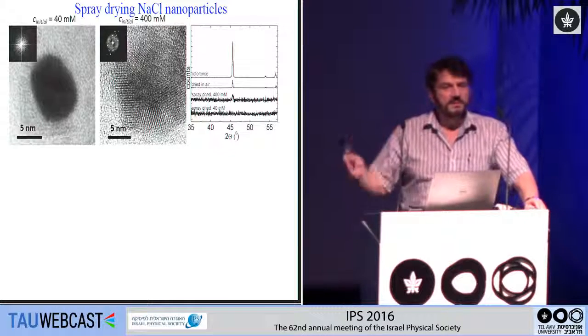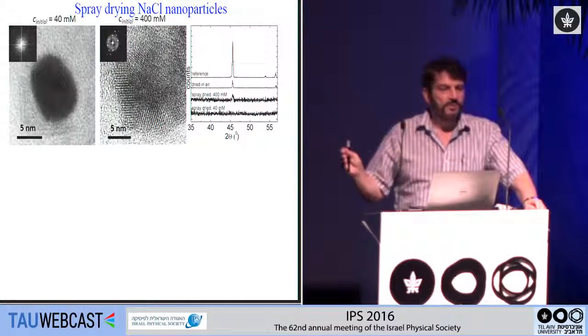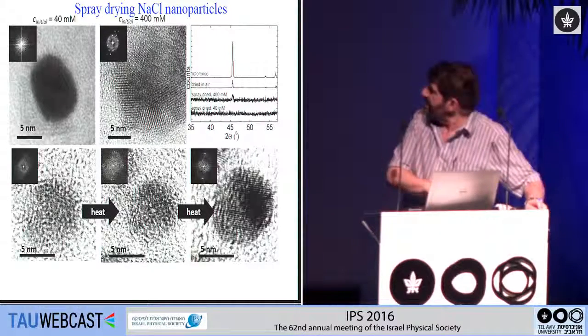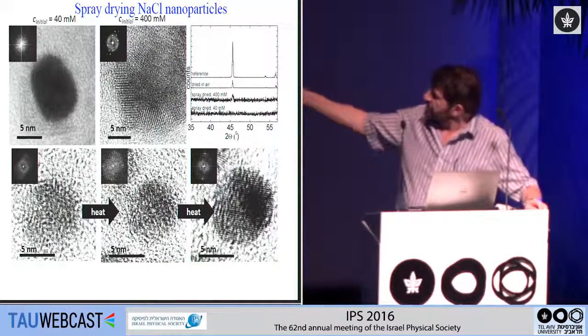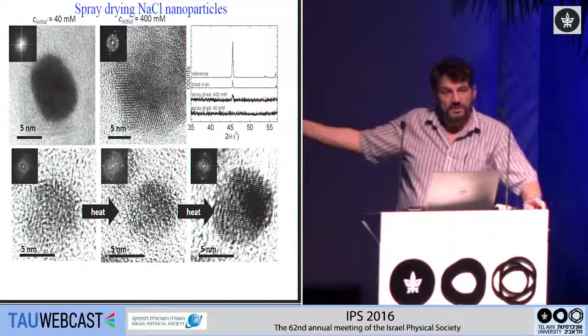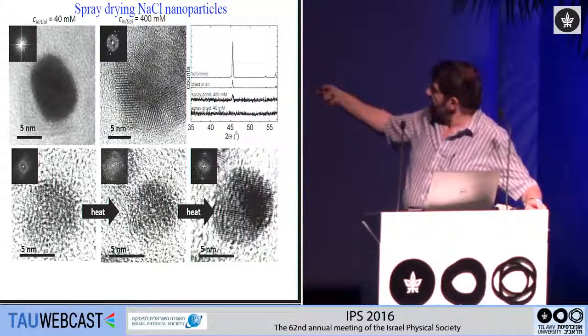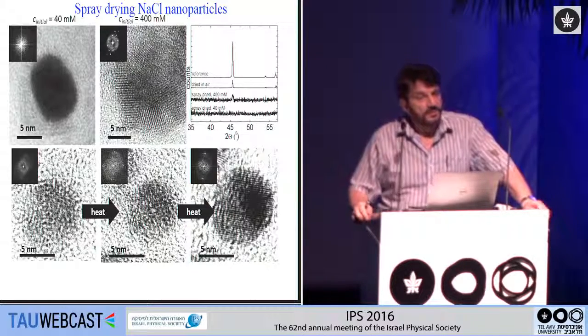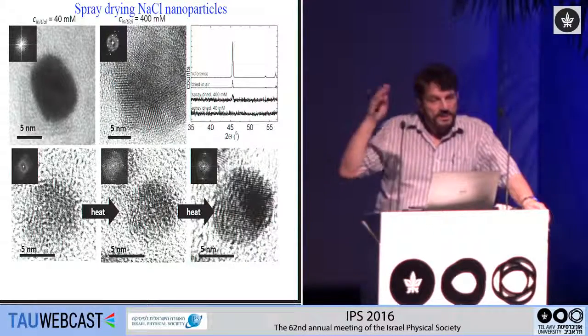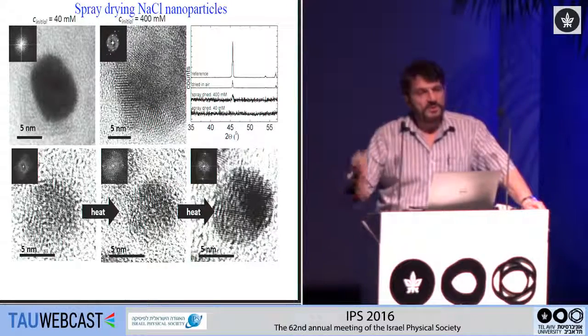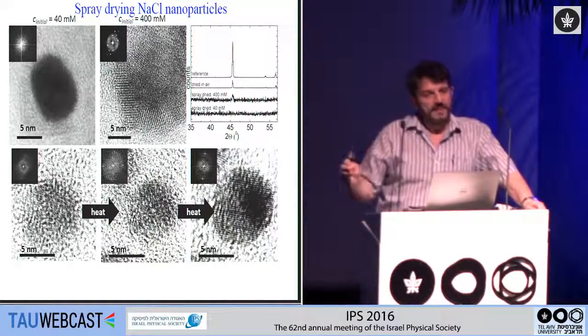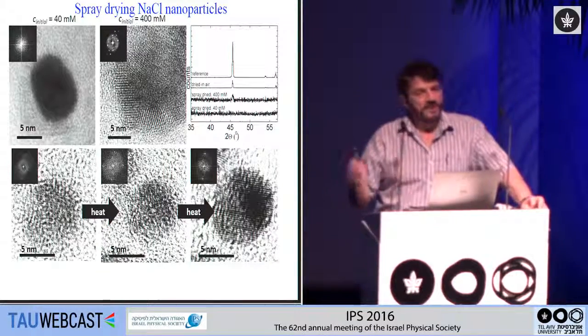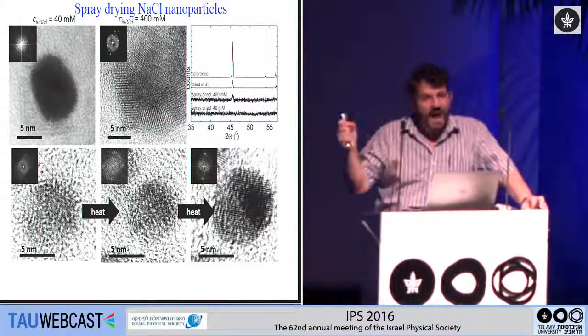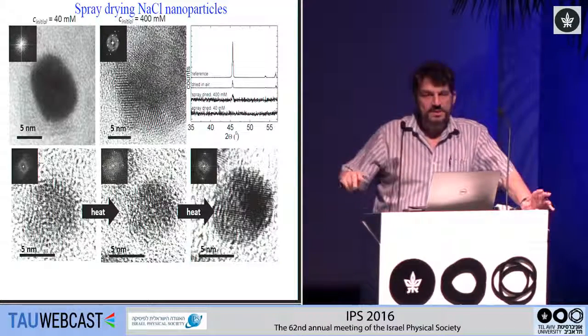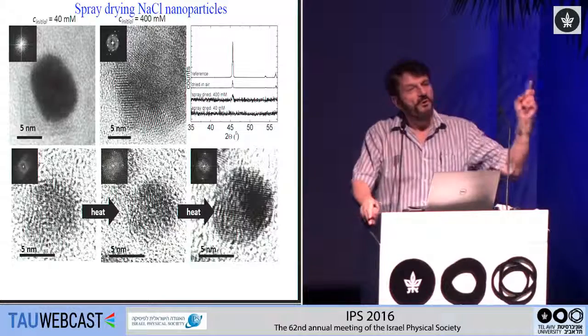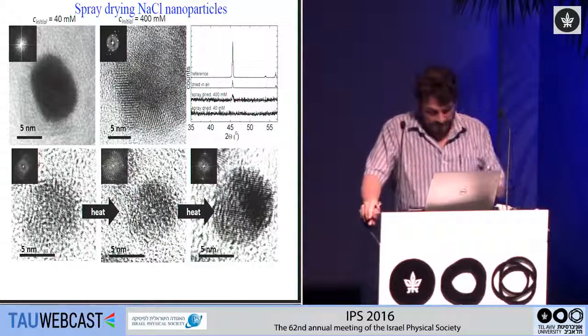If you make salt below 5 nanometers just by spray drying it, it's also amorphous. And here's some examples of the amorphous material. And just to prove that it's amorphous, we took an electron microscope and we heated it. And you can start to see that as you heat it, it starts to crystallize, and it forms the lattice of salt. So even something that is strongly crystalline as table salt can be made amorphous just by spray drying it with this type of spray dryer, with these tiny, tiny particles, by nebulizing it. So this is a very, very generic way of making both very small particles and making amorphous particles.